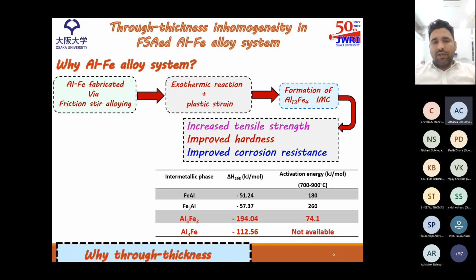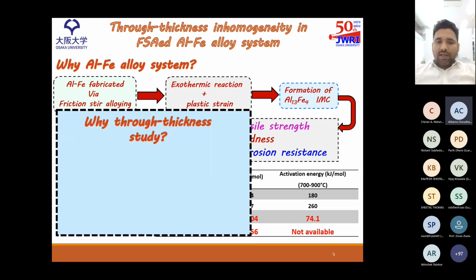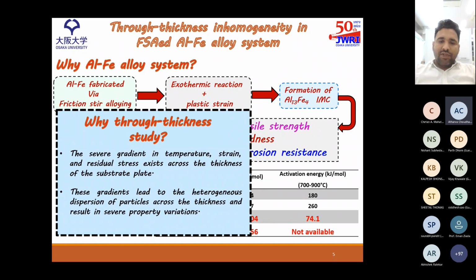Now another question: why through thickness and what does it mean? Through thickness means that in friction stir welding, when we are using the shoulder, the heat generation is not homogeneous. On the top surface where the shoulder is interacting with the base plate, the maximum heat is generated. And when we move across the thickness, the heat generation changes, the temperature varies, and similarly the strain and the residual stresses vary. So based on these